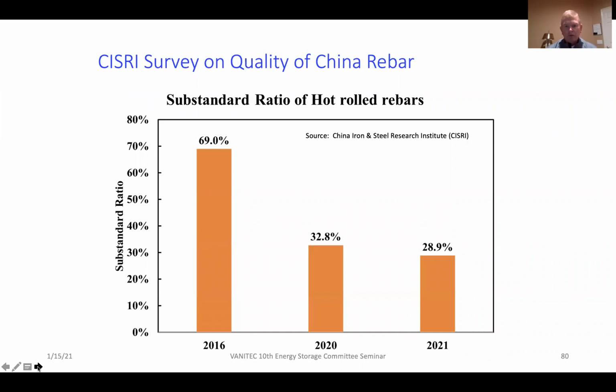This is another slide from our colleagues in China, which is quite interesting. The new rebar standard in China went into effect in November of 2018. And typically, it takes some time for the new standards to be fully adopted in China. In the past, we saw people producing high-strength rebar using quench and temper methods, which give you higher strength, but the ductility of the steel is not adequate to absorb the energy when we have seismic activity, and that's when we have catastrophic failure of rebar and buildings collapsing.